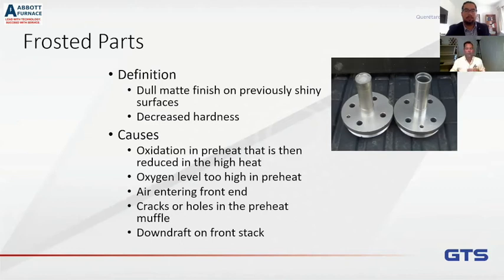So what's happened is you had oxidation in the preheat, okay? Or you could just have too high of an oxide level, or an air leak in the front end, or you could have a crack in the muffle, or a leak in that front air. Or it could be as simple as you have a downdraft coming down your stack. If the wind blows across the stack and it goes down the stack and into the furnace, it pushes air in the front of the furnace and oxidizes that part.